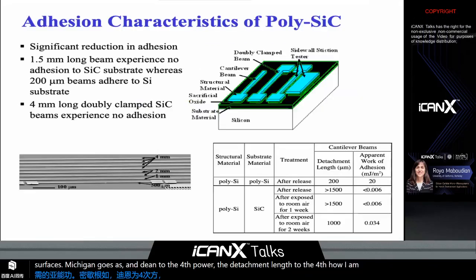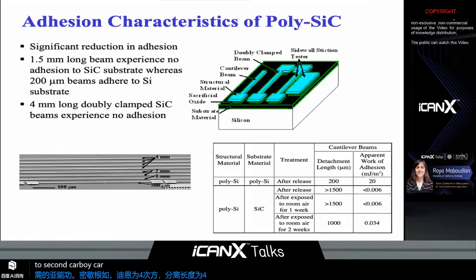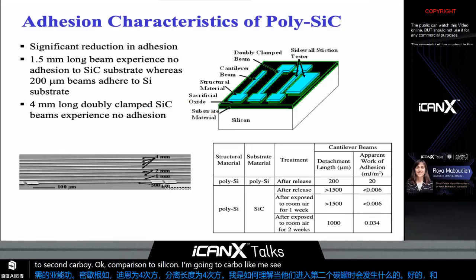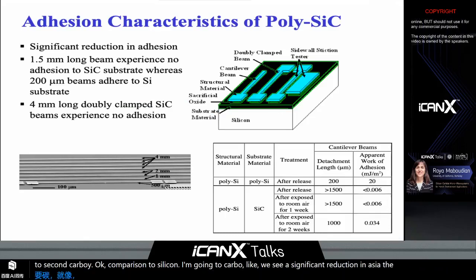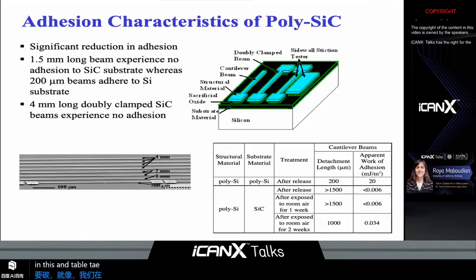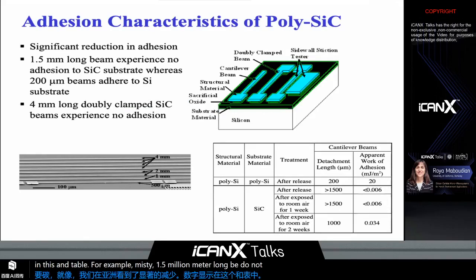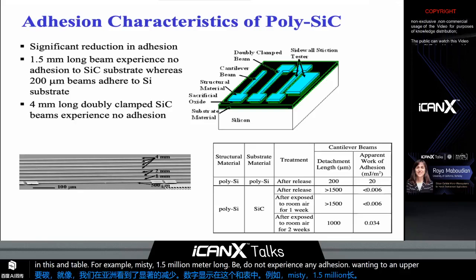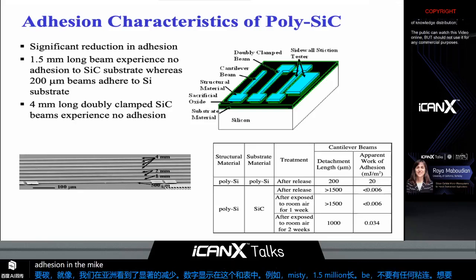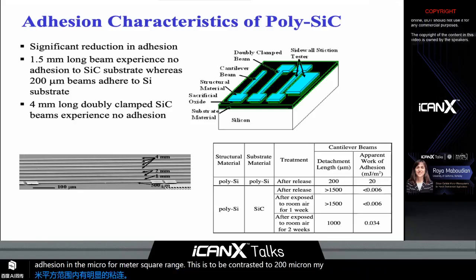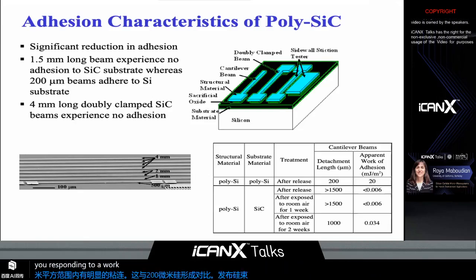Let's see what happens when we go to silicon carbide in comparison to silicon. By going to silicon carbide, we see a significant reduction in adhesion. The numbers are shown in the table. For example, we see 1.5 millimeter long beams do not experience any adhesion, corresponding to an apparent work of adhesion in the microjoule per meter squared range. This is to be contrasted to 200 micron polysilicon beams that remain adhered, corresponding to an apparent work of adhesion of tens of millijoule per meter squared.